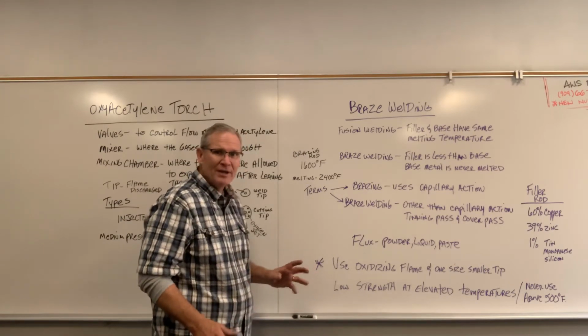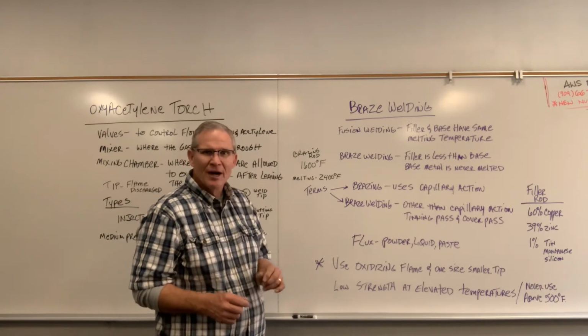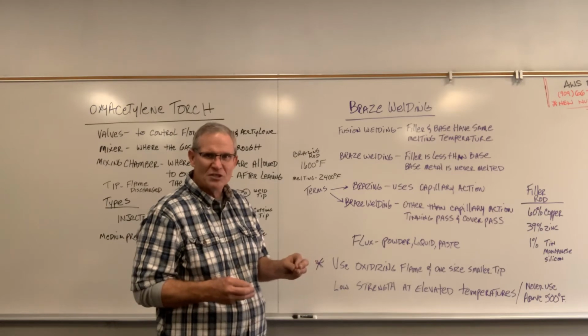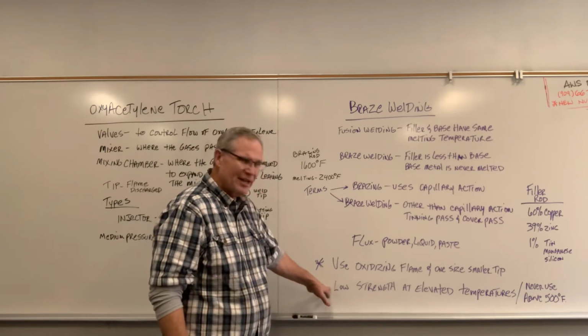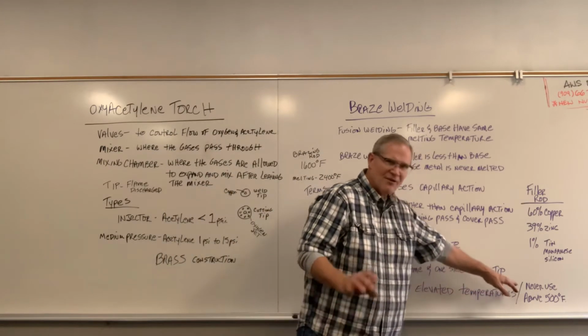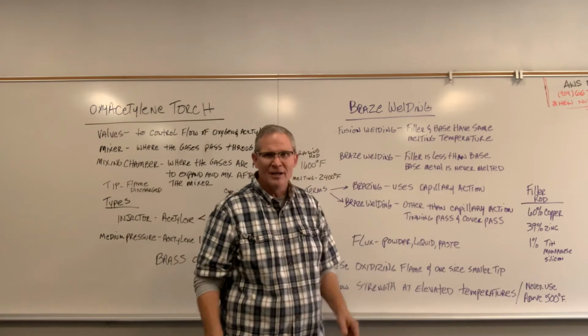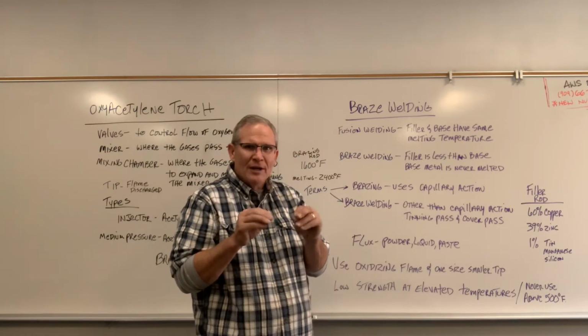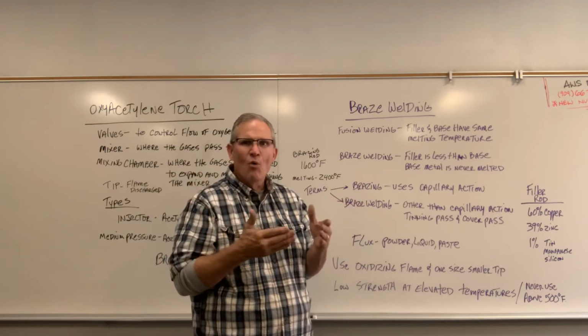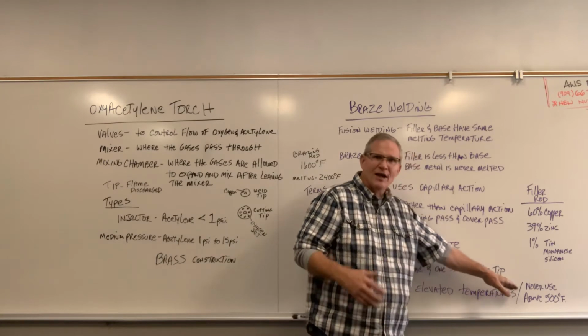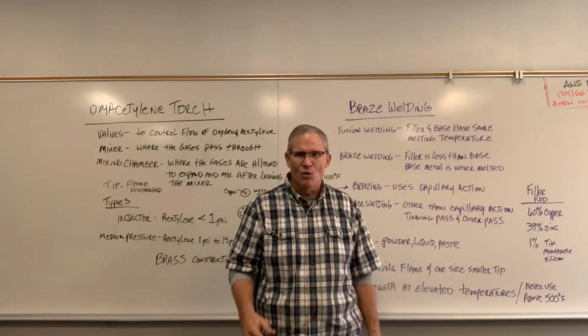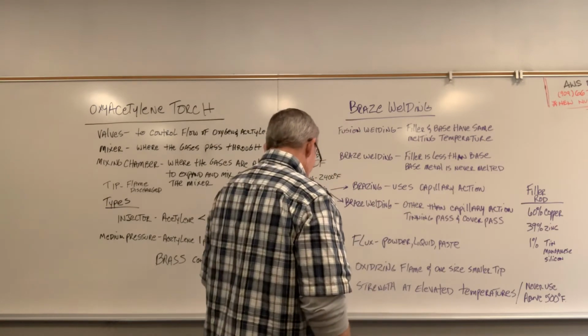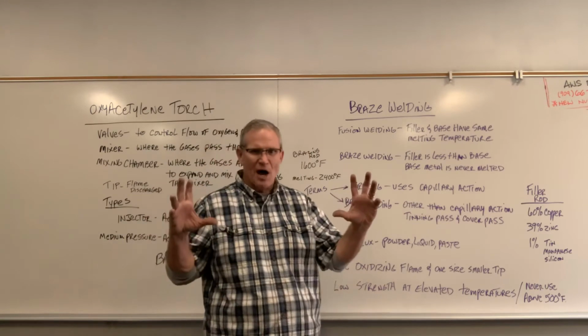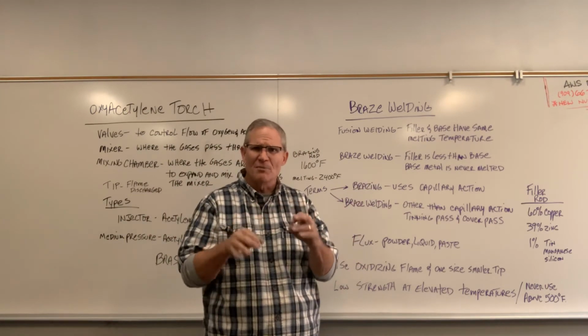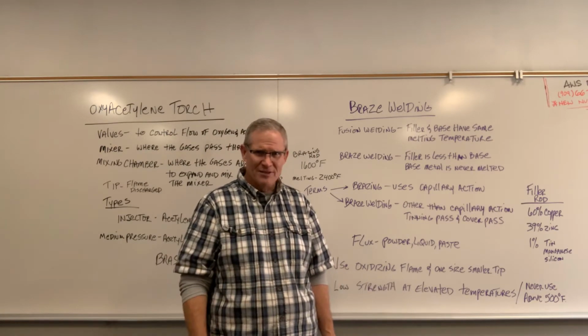If it's done properly, it's called microscopic fusion, and it's just as strong as the material itself. The only issue with braze welding is it has low strength at elevated temperatures. You don't want to put this in a situation where it's above 500 degrees Fahrenheit. Whatever you're braze welding, the surrounding atmosphere around it, you don't want to raise above 500 degrees Fahrenheit. It could actually fail the weld that you've done. So keep that in mind. I've actually welded cast iron sprockets, beveled them and brazed them all together. It works very well and gives it plenty of strength.